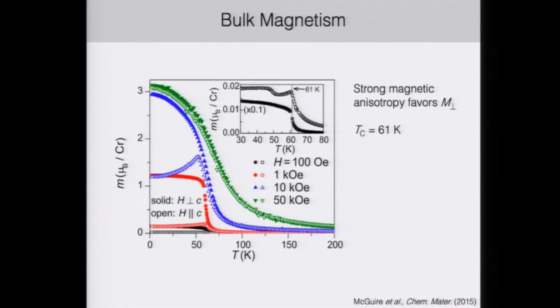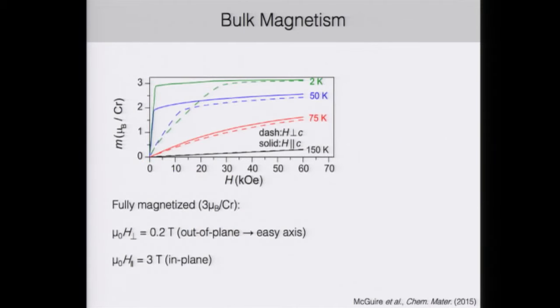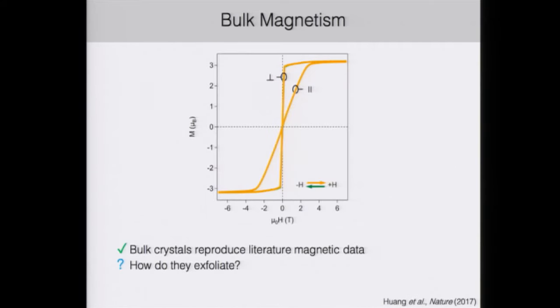So the strong magnetic anisotropy favors the out-of-plane magnetization, and we have a Curie temperature of about 61 Kelvin in the bulk. So as I said before, it's fully magnetized with about 3 Bohr magnetons per chromium site, and so it has this out-of-plane easy axis and requires a rather large magnetic field to pull the moments in the in-plane direction. We performed bulk magnetism studies ourselves on the crystals that we grew, and they reproduced the literature magnetic data quite nicely. So now we want to know, how do they exfoliate?